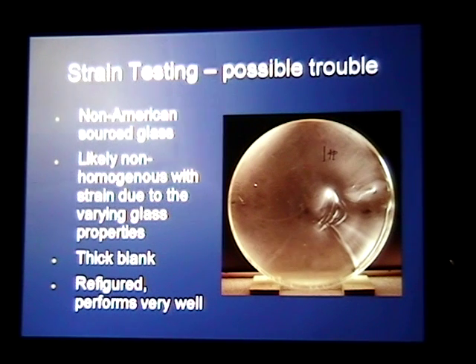I told the owner, you know, I can't guarantee it's going to stay this shape forever, but I can definitely refigure the glass, and I think it'll be pretty darn good. And it turned out he was extremely satisfied with the mirror, because it's fairly thick. The other thing you have to think about is the thicker the glass, the more of a brightness variation that is permissible, because it's measured in strain per thickness of glass, microns per centimeter. So this one stayed, and to this day, a year or so later, is still performing admirably. I think this was a 14-inch blank.